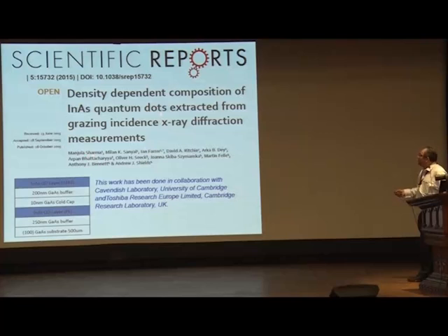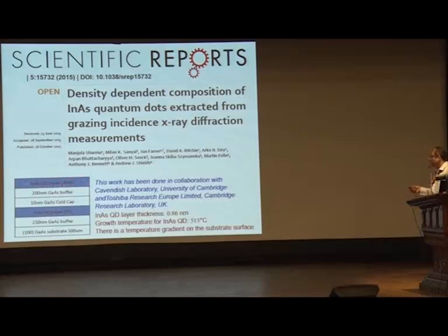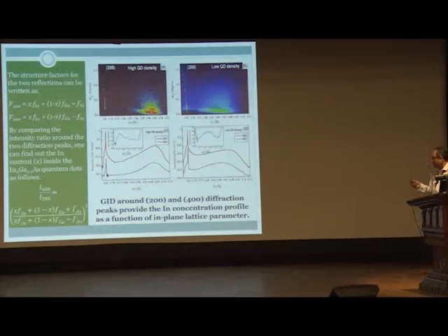The problem still remained there in the sense that photoluminescence comes from the bottom quantum dot layer, and the structural information comes from the upper layer, and the assumption is these two are conformal, and the information you get from photoluminescence and the information you get from the AFM measurement and X-ray measurement can be correlated. So that was the problem which we stated in our paper. Nevertheless, the technique went through very nicely.